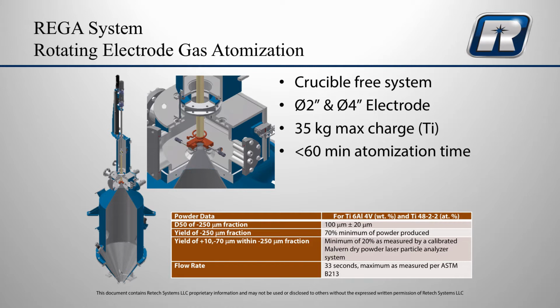Depending on if it's an additive manufacturing process or a metal injection molding process, the end customer then starts looking at the degree of very fine powder that can be produced in the process. But right now what we're saying is that for a yield of the plus 10 micron to minus 70 micron, we'll guarantee a minimum of 20% yield for that size fraction within the minus 250 fraction range. And again, the flow rate of the powder is actually quite good for the additive or bed manufacturing processes.